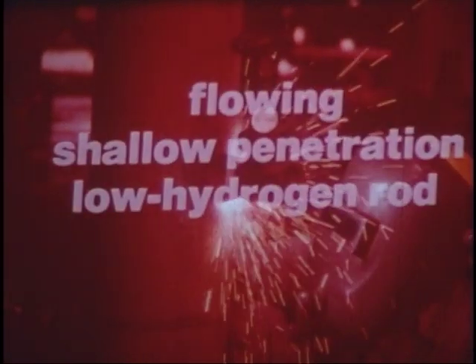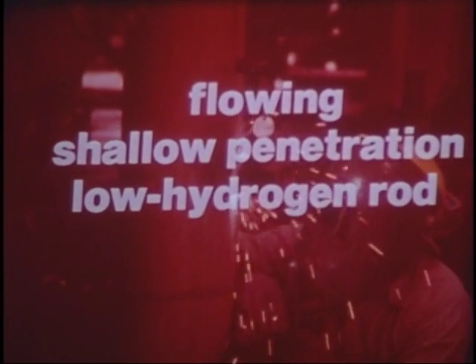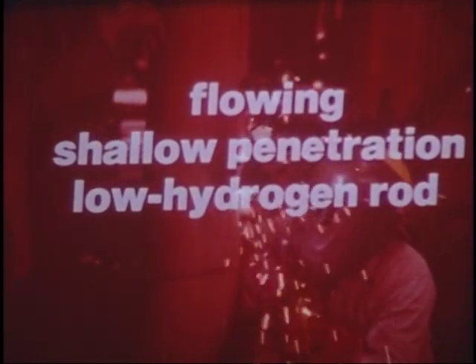Blow-through, a hazard to hardline welding, occurs when the weakened pipe material under the welding molten pool is blown out by the internal pipe pressure. Blow-through can be prevented by observing a few basic rules. The content of the line should be flowing, and only a shallow penetration, dry, low hydrogen rod should be used.